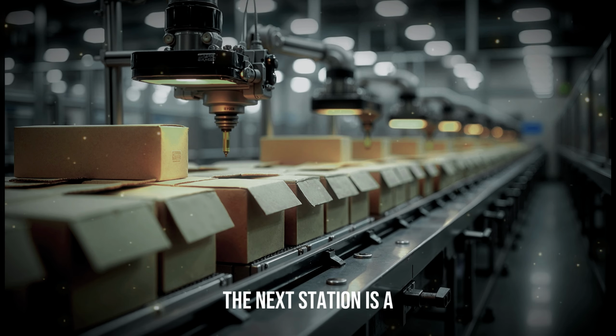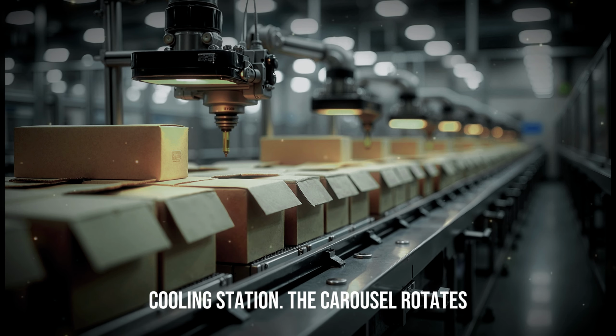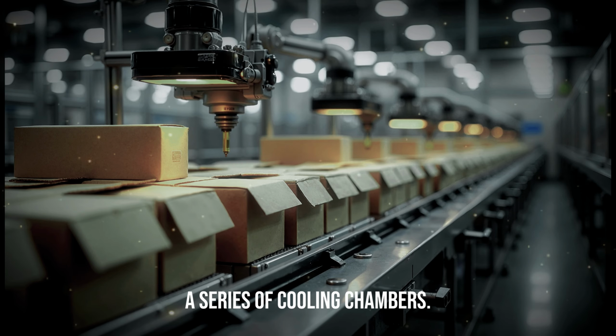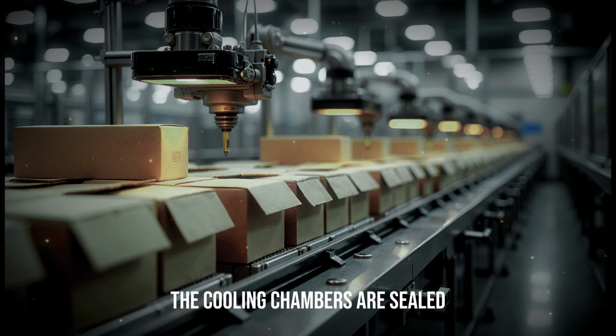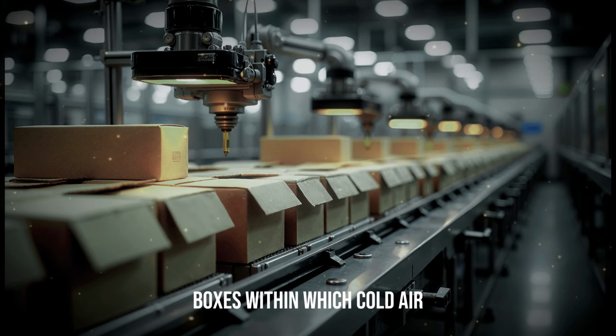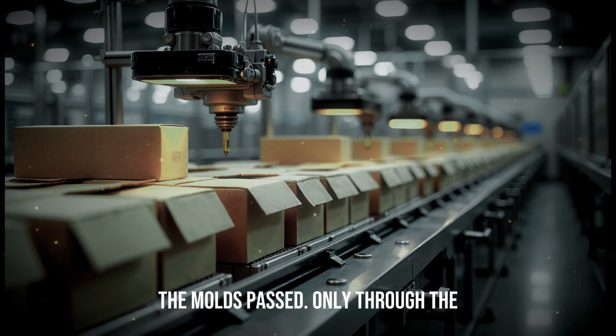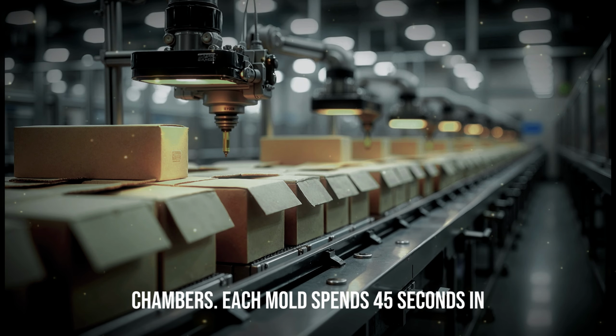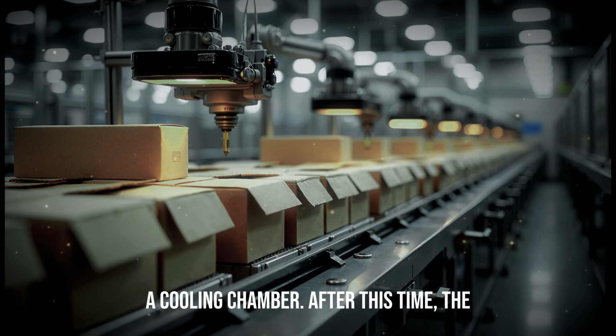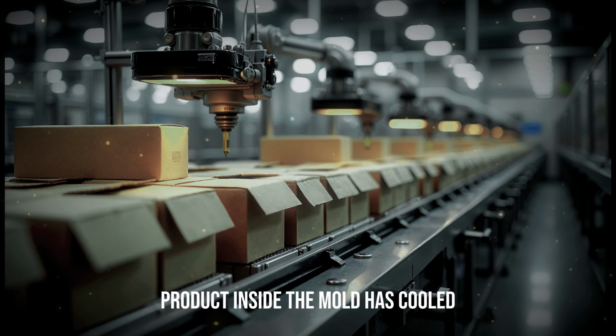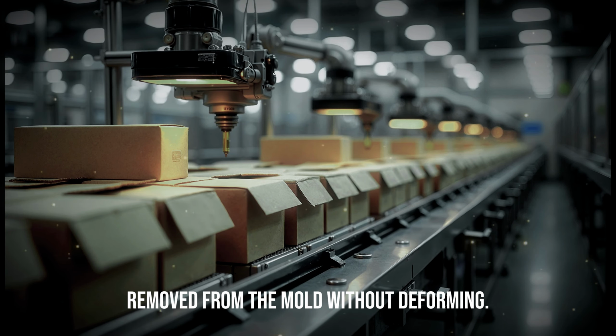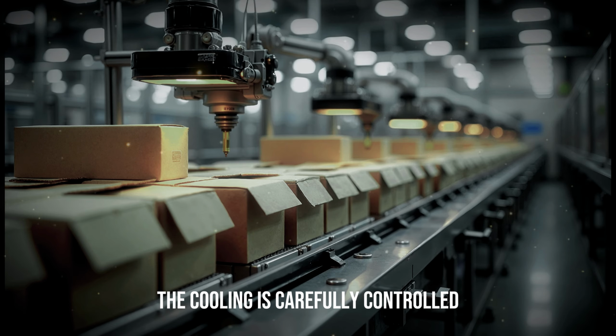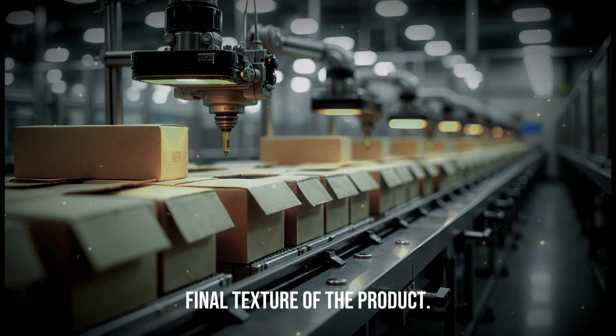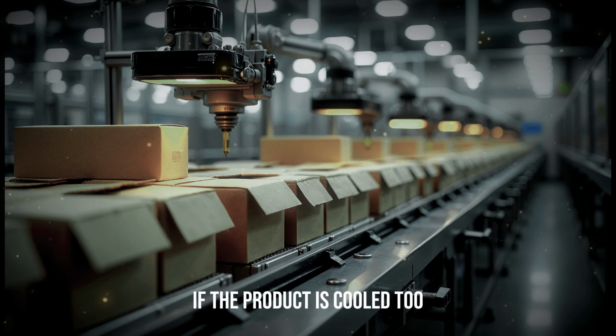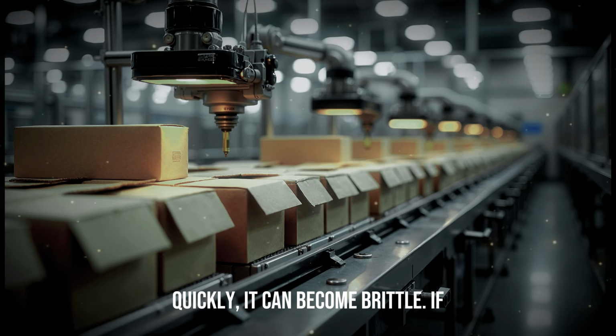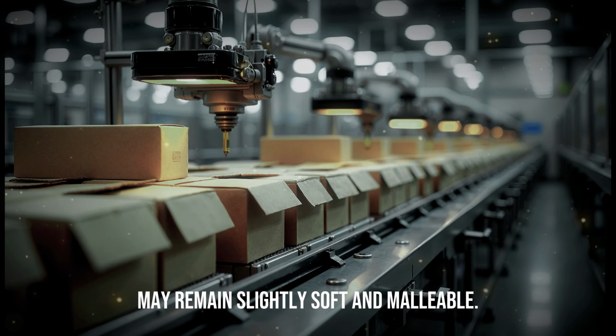The next station is a cooling station. The carousel rotates continuously, passing each mold through a series of cooling chambers. The cooling chambers are sealed boxes, within which cold air at 5 degrees Celsius is circulated continuously. The molds pass slowly through the chambers. Each mold spends 45 seconds in a cooling chamber. After this time, the product inside the mold has cooled sufficiently that it can be safely removed from the mold without deforming. The cooling is carefully controlled because the rate of cooling affects the final texture of the product. If the product is cooled too quickly, it can become brittle. If it is cooled too slowly, it may remain slightly soft and malleable.